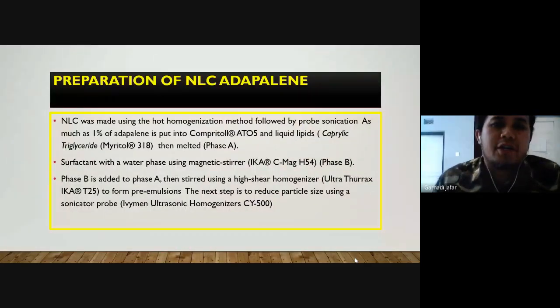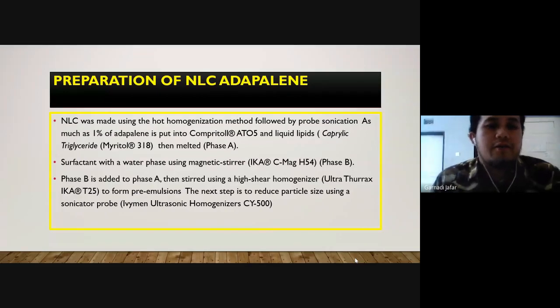This is the preparation of NLC adapalene. NLC was made using the hot homogenization method, followed by probe sonication. As much as 1% of adapalene is put into Compritol ATO and liquid lipid caprylic triglyceride or Myritol, then melted (Phase A). Surfactant with a water phase using a magnetic stirrer, (Phase B). Phase B is added to phase A, then processed using a high shear homogenizer or Ultra-Turrax to form a pre-emulsion. The next step is to reduce particle size using a sonicator probe.